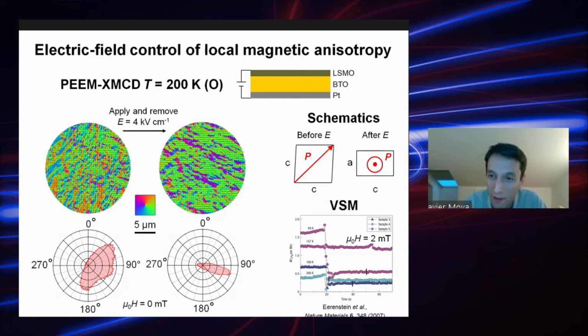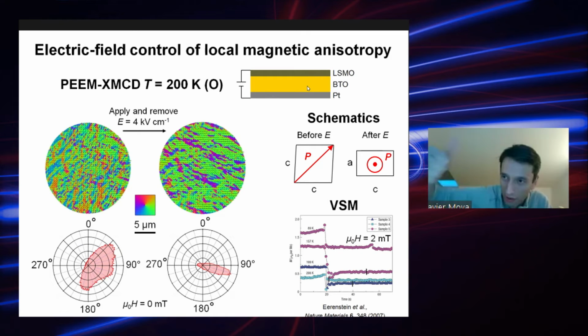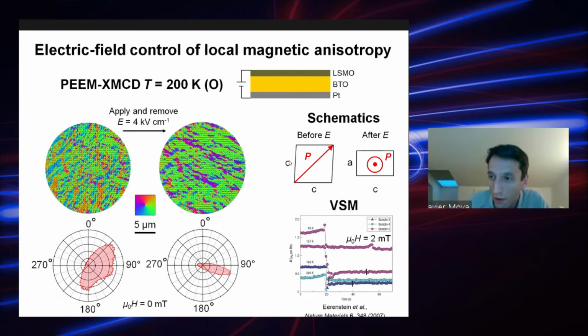And the mechanism, as we understand it, is that if you start in an orthorhombic phase, where again the polarization is mostly in plane, when you apply an electric field out of plane, because this is the configuration, so we have LSMO, barium titanate, and then a bottom electrode, so the electric field is out of plane. When you apply the electric field out of plane, the polarization rotates out of plane. So you are changing the strain that the film is seeing.